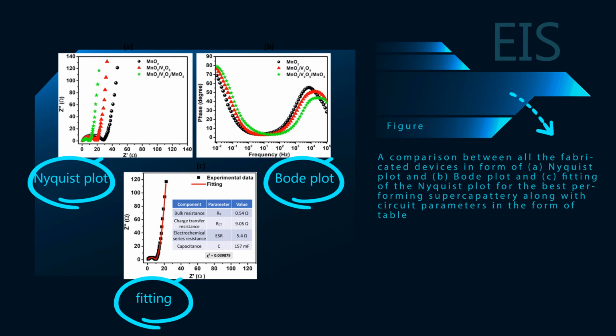Here in figure A, the EIS data was used to draw the Nyquist plot of the fabricated supercapattery, and figure B shows the phase versus frequency graph, also known as the Bode plot, used in investigating the capacitive or resistive nature of the device. The phase angle close to 90 degrees at the lowest frequency indicates the capacitive behavior of the device. And in figure C, the theoretical curve fits very well with the experimental data.